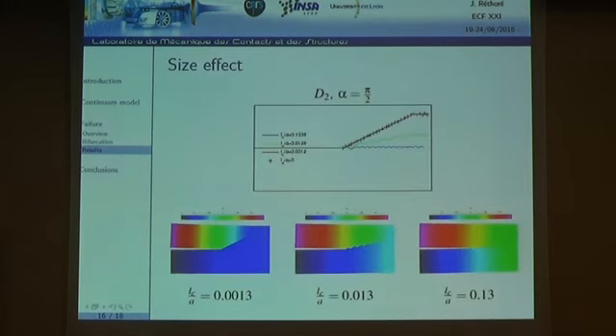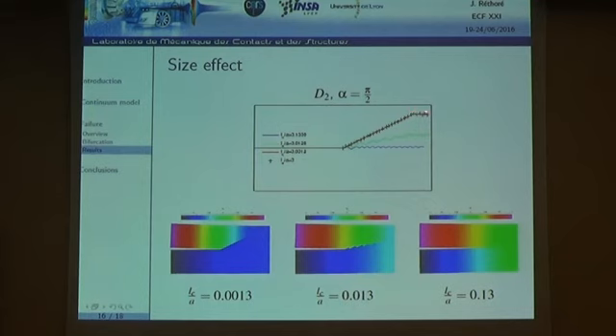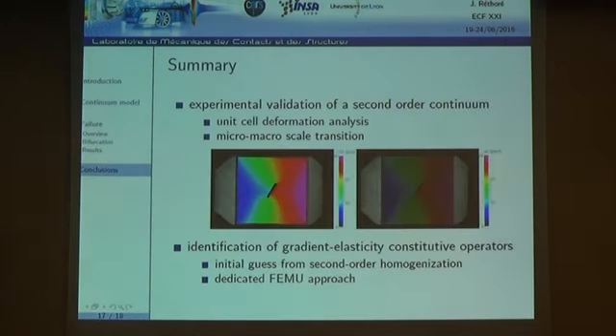Playing with the unit cell size in numerical simulations, we observe a strong influence on results: increasing the unit cell size by a factor of 10 changes the fracture trajectory, and increasing it by a factor of 100 produces a distinctly different crack path. This demonstrates that the model can account for the effect of the microstructure on the crack trajectory.